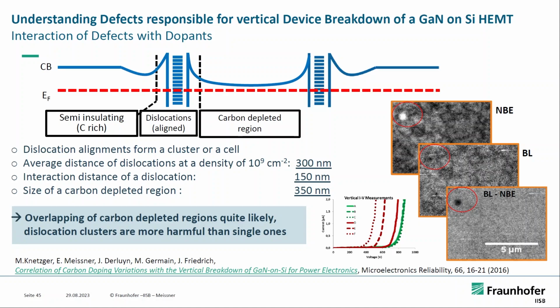So what you see is, if you imagine that this is a dislocation, around the dislocation the carbon content is, let's say, getting gathered to the dislocation. So the carbon moves to the dislocations, just inside the strain field of the dislocation.